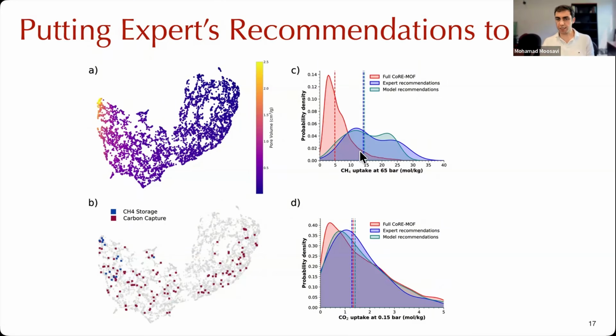And in fact, the recommendation from experts is very good in this case. In contrast to carbon capture, where the recommendation from experts, the blue, is not that much better than just a random sampling from the entire database. The reason that we think this is happening is that first, it feels like carbon capture is more complicated than methane storage. The performance indicators are not easy to define. Usually you need to evaluate a material at the process level to understand its performance. So there are various reasons that one might claim a material is good for carbon capture versus the others. And also, probably the field of carbon capture was hotter over the past decade, so that made people claim victory for various reasons that are not entirely practical.